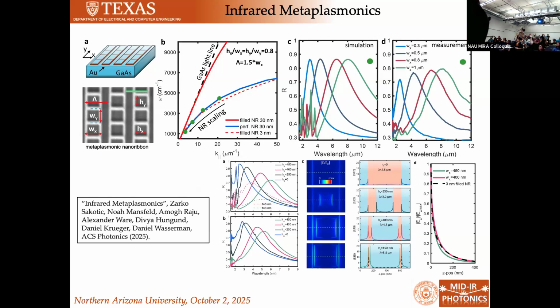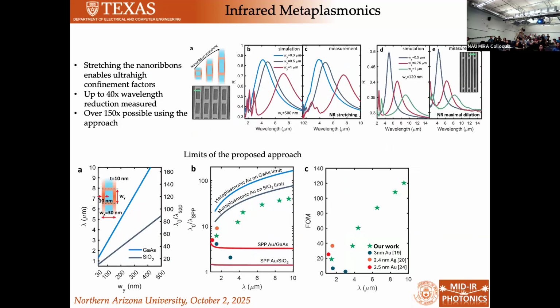These are nano ribbons. You can look at our mode confinement. It's on the order of lambda over 30, lambda over 40. We think we can hit lambda over 100 or lambda over 150. So we can take 5-10 micron light and we can condense it down to the nanoscale. Now we can start thinking about how we can interact that light with quantum systems and single quantum emitters and these sorts of things in the infrared. Right? We can stretch these, and that enables essentially tuning of our resonance, right?